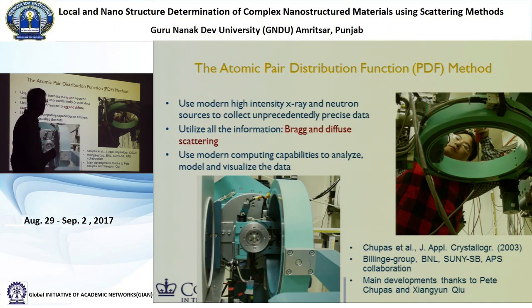But one step that helped that was actually the use of high-intensity X-ray sources. And we would go to CHESS, which is the high-energy synchrotron at Cornell, which is in New York State, about 4 hours away from New York City. And we would put our sample in the beam, and you have to collect data over a very wide angular range to get the high Q that we're after. We would have a point detector, so we would move it one point at a time. And it took a really long time. We would collect data for hours and hours. So one data set for 12 hours.